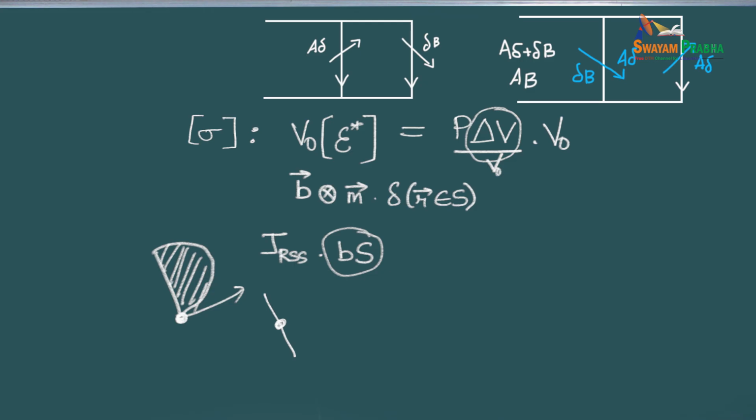It's not really physical because this is a mixture. It is a mixture of the relative variation of the volume of the vacancy multiplied by its volume itself. So this would be the initial volume of the vacancy, and this would be the eigenstrain related to the vacancy itself. So the activation volume is not a physical volume here. It's a product of both the eigenstrain and the initial volume, and it's basically the difference between the volume that the vacancy would like to have compared to the volume it has before relaxation.